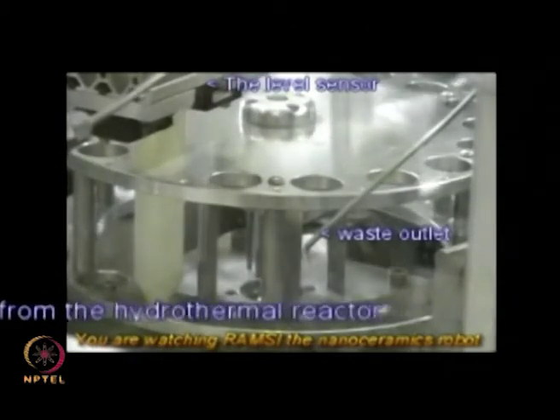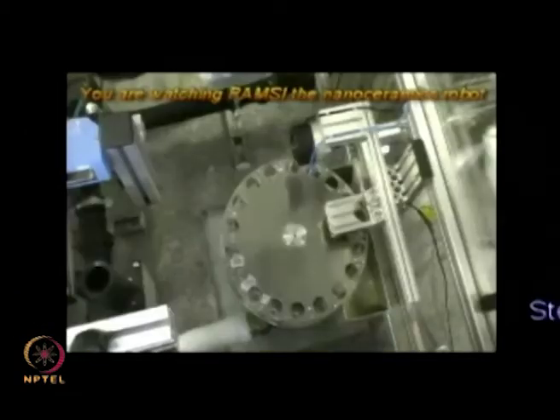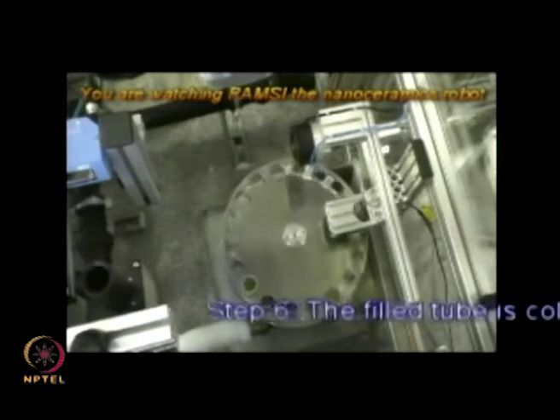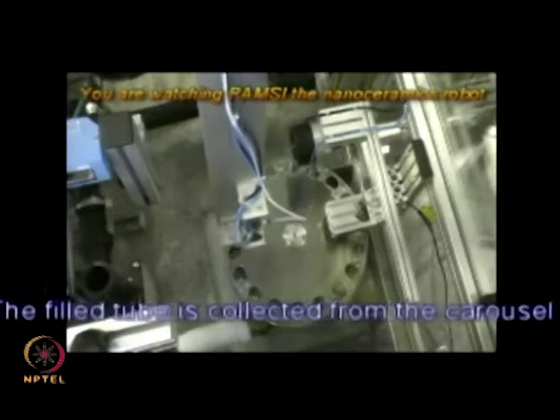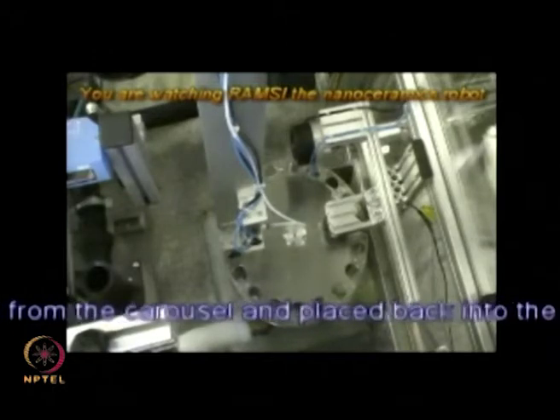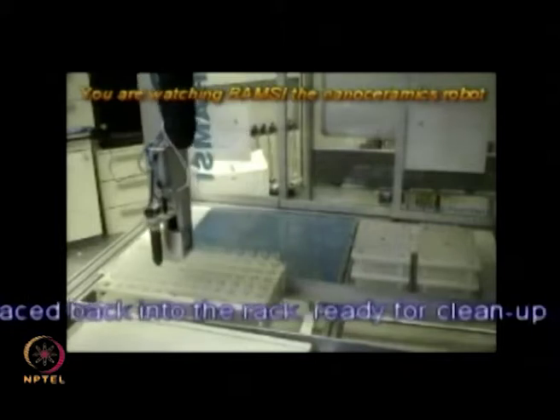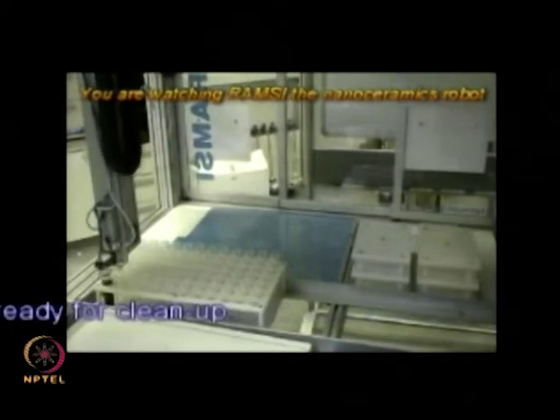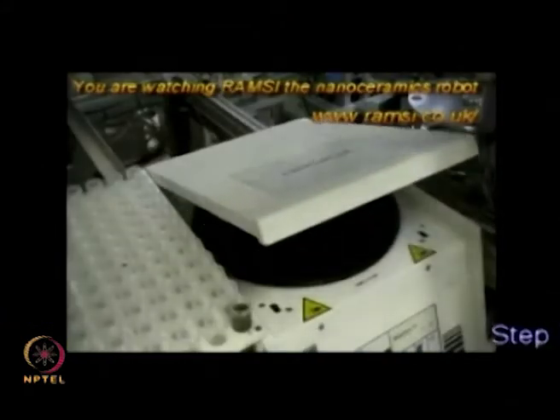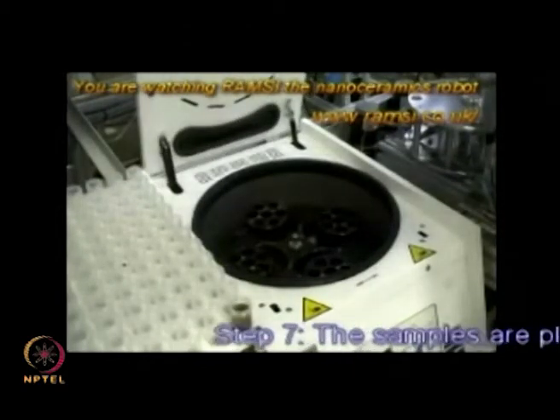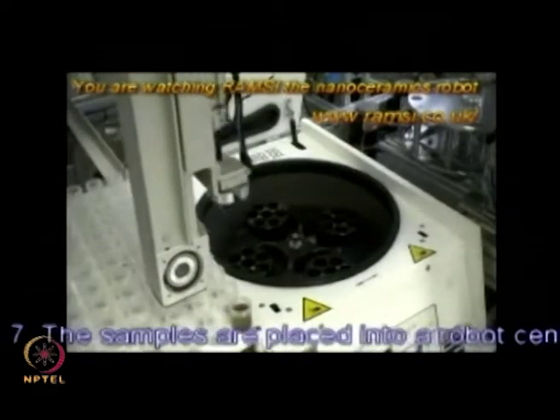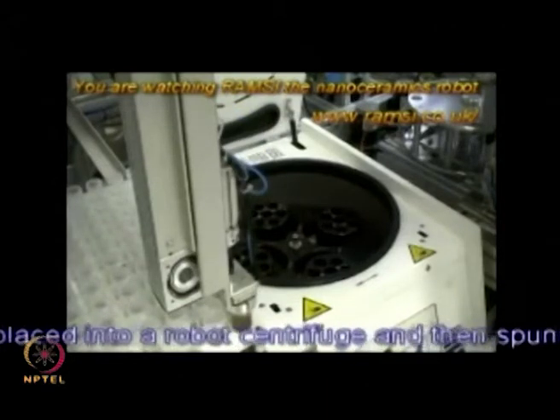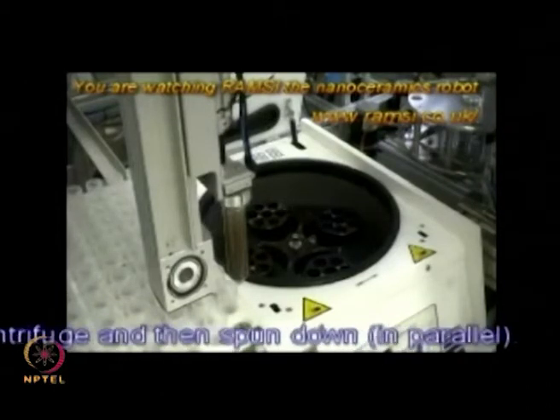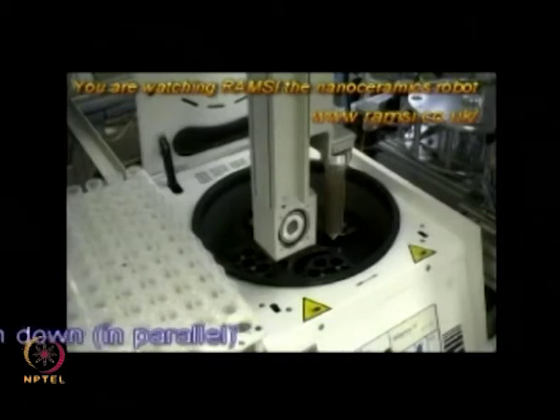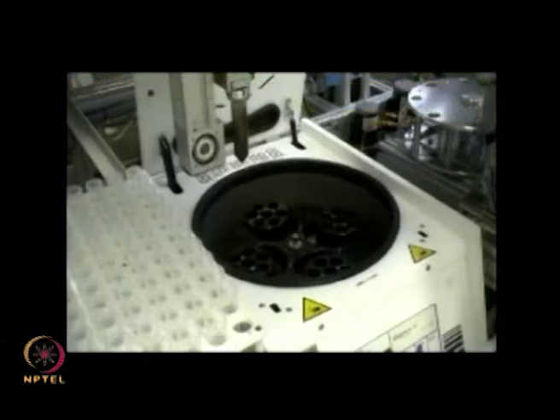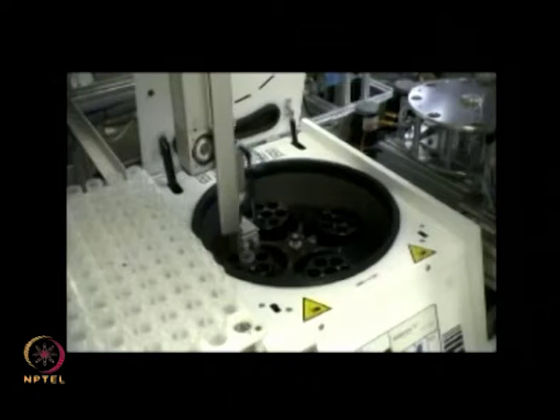All of this process is non-contact because it's done in ultra clean rooms, because even a small amount of dust particle would cause heterogeneous nucleation. Look at the color of the suspension, it is black. This will be ultracentrifuged at the next step. It is picked up remotely, placed into the ultracentrifuge, and this is not one tube, this is a demo video. So, they are showing you only one tube. In reality, at a time 100 tubes are centrifuged.